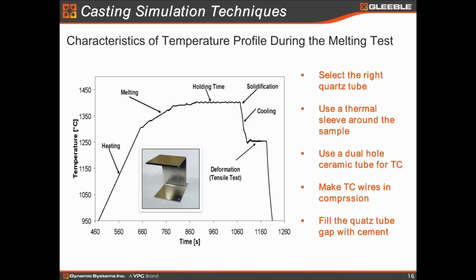So one way to minimize this thermal gradient is to use a thermal sleeve around the quartz tube to minimize the radiation and the convection. That way the temperature you measure at the surface will be equal to the center. That way, whatever you measure is what you see in the melting zone. And also, when we insert a thermocouple in the liquid zone, it's very hard to have the thermocouple stay in the liquid, right? So that is very important.